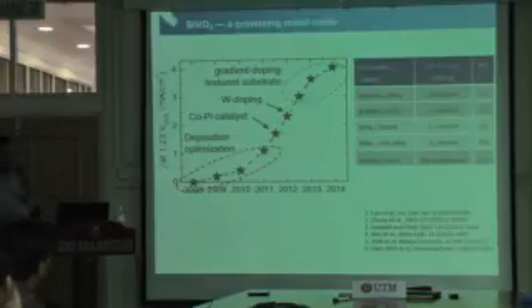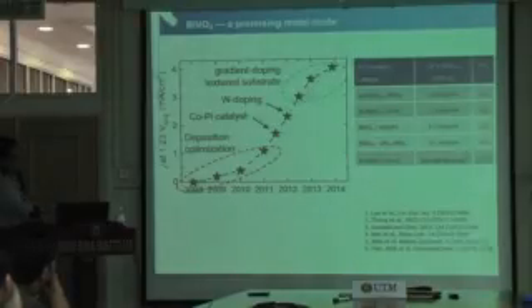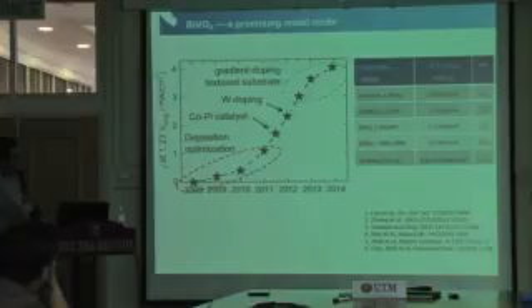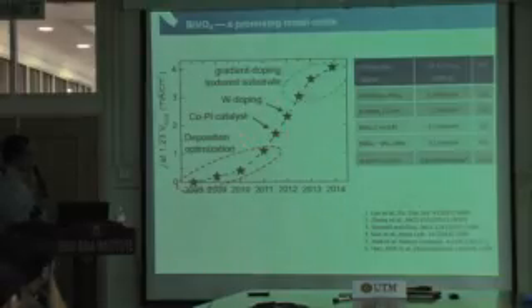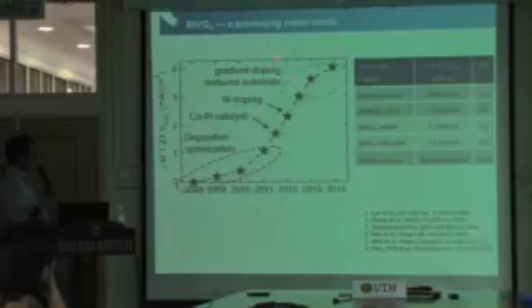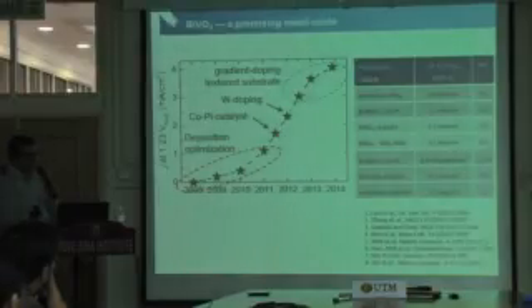Alright, so I talked a lot about bismuth vanadate already, and this plot over here sort of summarized the progress that we did in our lab on bismuth vanadate. At the beginning, we worked a lot on optimizing the deposition parameters, so our progress is rather slow or gentle. And once we actually started to analyze the performance limiting factors, catalysis, conductivity, charge separation, we started to increase the performance much further. In fact, at that point, we got one of the best performing bismuth vanadate-based photoelectrodes until other people came and overcame this